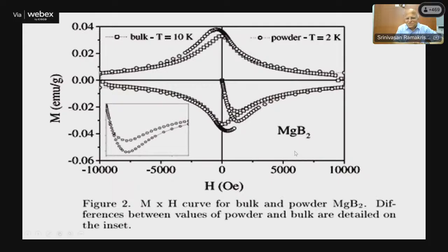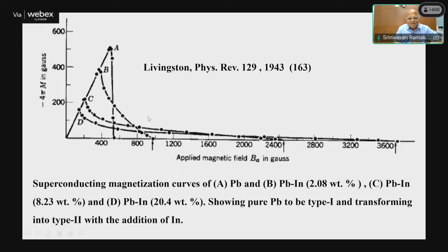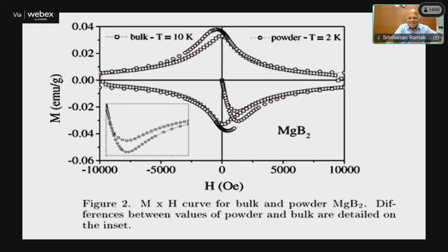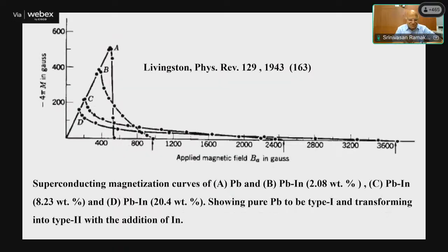So this is MgB2, another superconductor, with a really high 39 Kelvin superconductivity. This is the four quadrant magnetization. Initially it goes like this, then it becomes positive because of flux pinning. Then you reverse the field, and it is still positive. And when you go back to the last quadrant, it has this kind of behavior. So it's like a hysteresis loop. This whole phenomenon is happening because you have disorder and pinning, whereas in the earlier system I showed you, there is very little pinning. So we can see the type 1 to type 2 behavior very nicely, whereas these are extreme type 2 superconductors. So the magnetization will behave differently depending on whether you have a type 1 or type 2 superconductor.